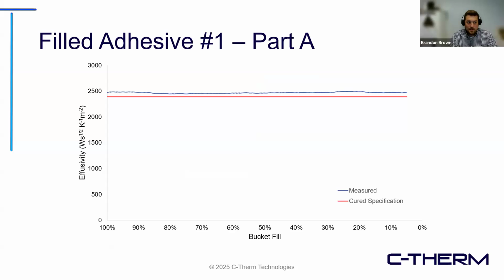So here is the first trial installed in one of the production lines with filled adhesive, very similar to the expired bucket that we had later, but this is not expired, obviously. This was collected with Till and his group at HELLA Forvia. This is just one run. Many of the runs of this number one sample looked similar. Again, the cured specification line is shown, converted using the heat capacity and density from the TDS.